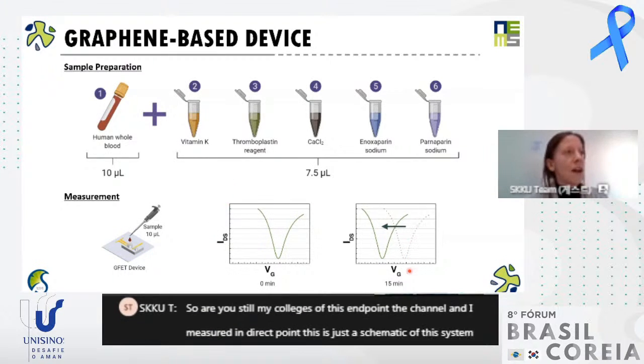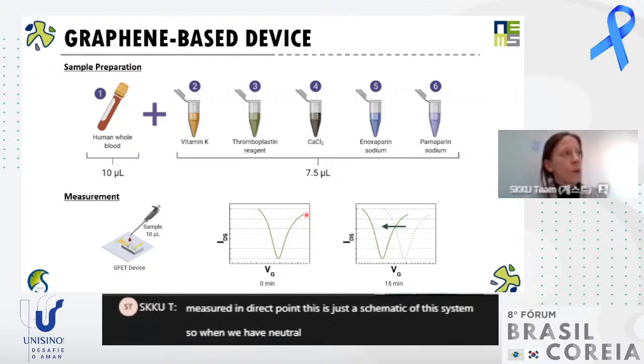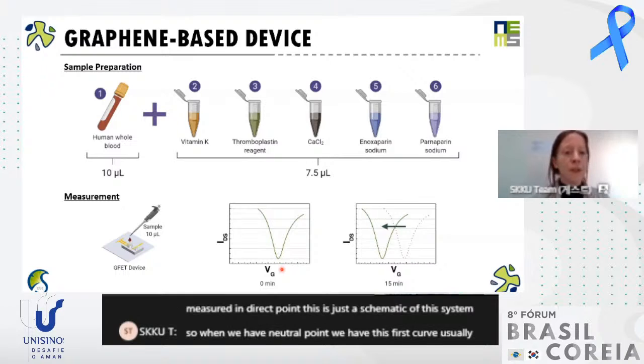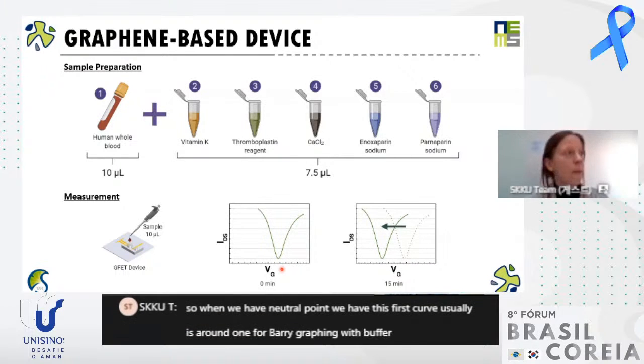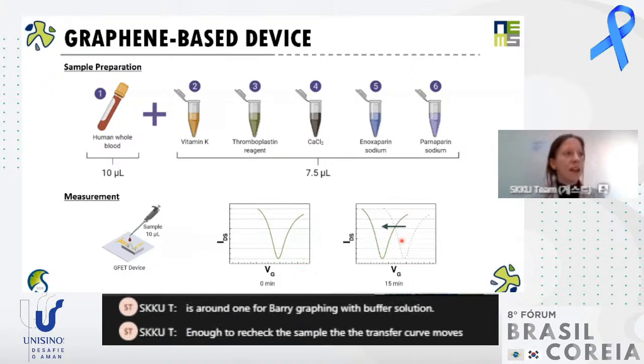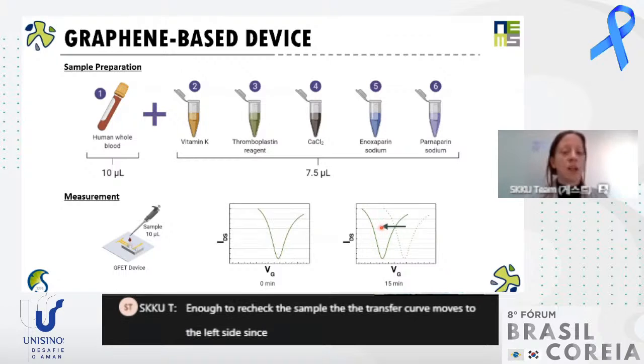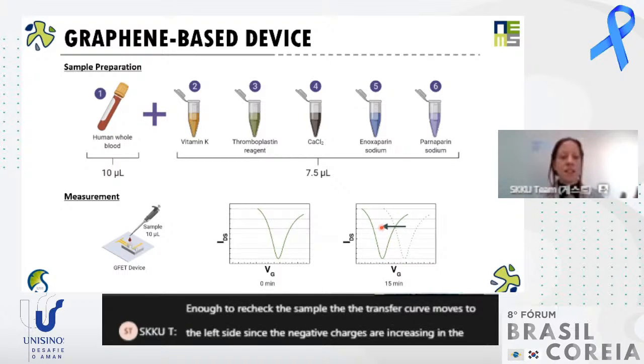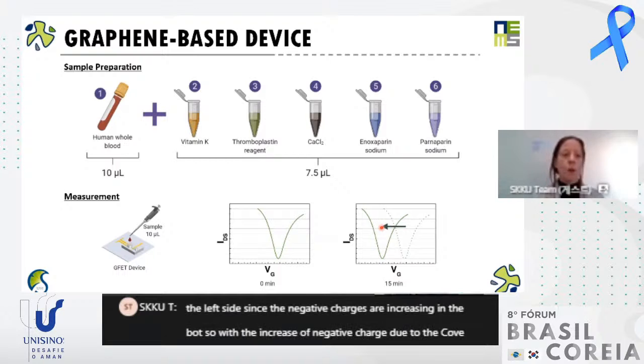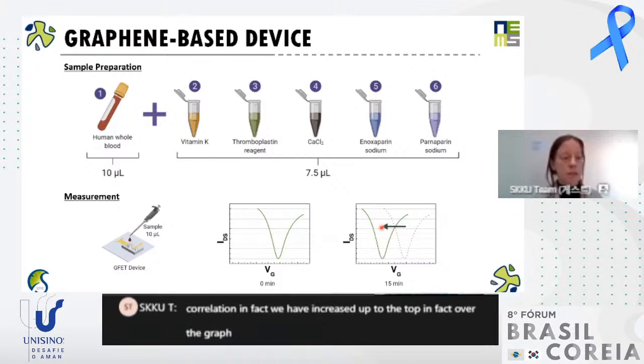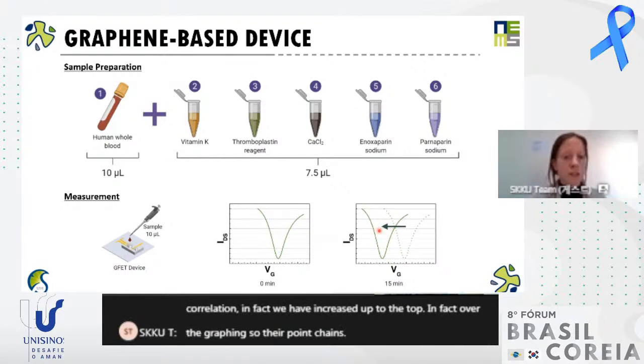So when we have the neutral point, we have this first curve. It usually is around 1 for bare graphene with a buffer solution. And after injecting the sample, the transfer curve moves to the left side since the negative charges are increasing in the blood. So with the increase of negative charge due to the coagulation effect, we have an increase of the doping effect of the graphene. So the Dirac point changes. In this case, it shifts to the left side.